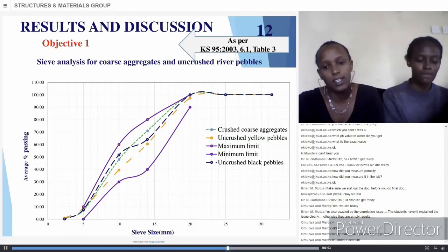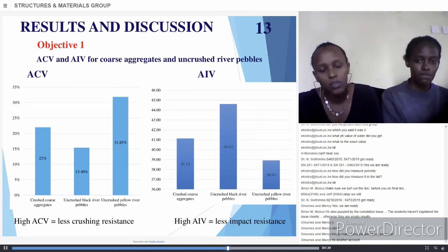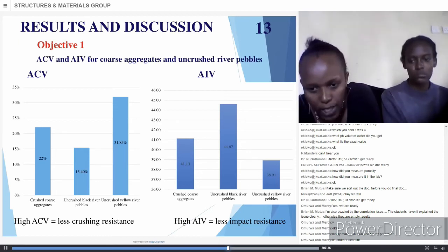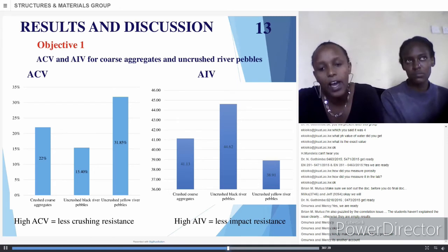From objective 1, the sieve analysis of the aggregates, that is coarse aggregate, crushed coarse aggregate and uncrushed river pebbles, the particle distribution was good and they fall within the envelope. Also from objective 1, the properties: the ACV for the yellow pebbles was high, meaning it has less crushing resistance. And for AIV, the uncrushed black pebbles had a high AIV, meaning they had less impact resistance.